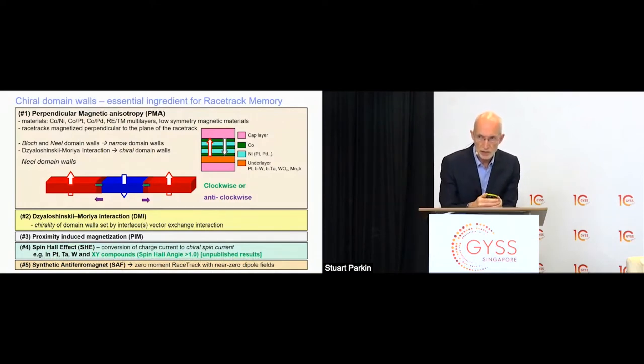First of all, we make the racetrack from, as you see on the top right, these green and blue layers that correspond to atomically thin layers of cobalt and nickel. Each layer is just a few angstroms thick, and the whole racetrack is only 1 nanometer thick. It's grown on a platinum underlayer shown here as orange. And the platinum underlayer not only gives rise to this spin Hall effect, where current passed through that material generates a spin current, but it also gives rise to a very interesting exchange interaction, which is called a Dzyaloshinskii-Moriya exchange interaction that causes the magnetic moments in the magnetic layer on top of the platinum layer to want to be oriented perpendicular to one another.